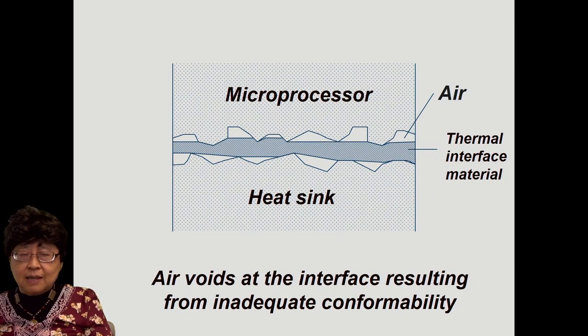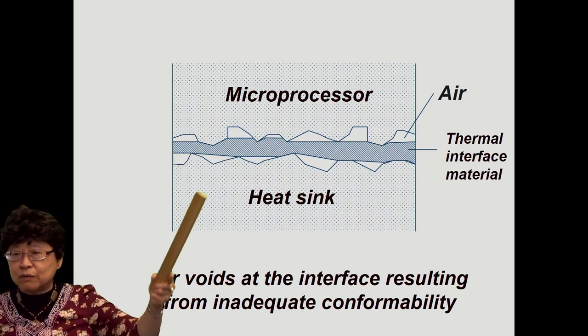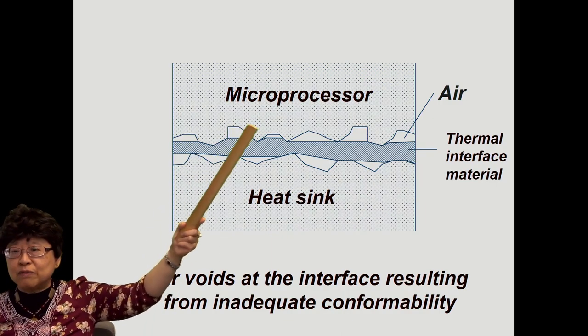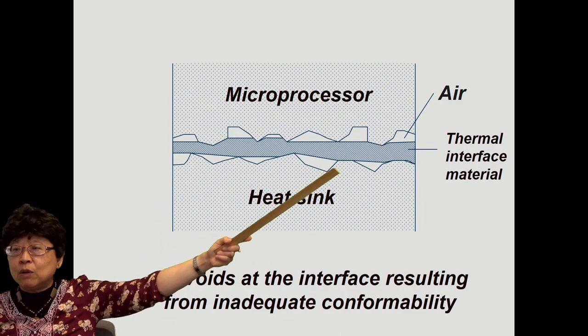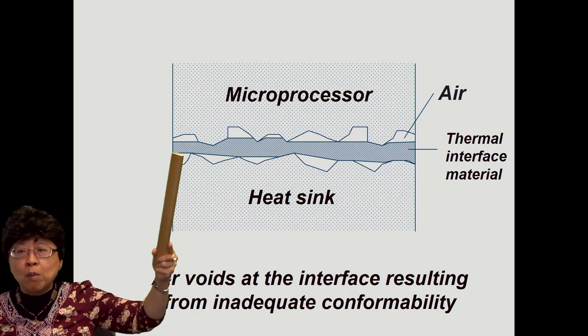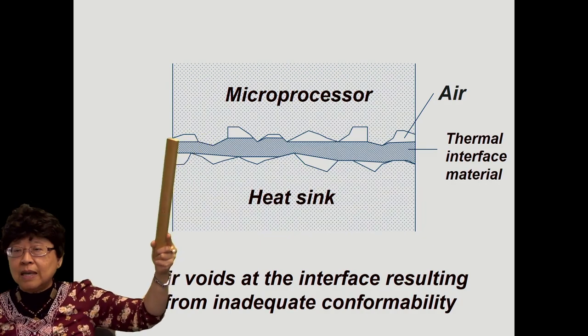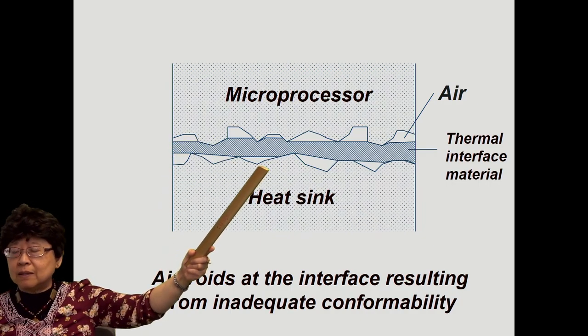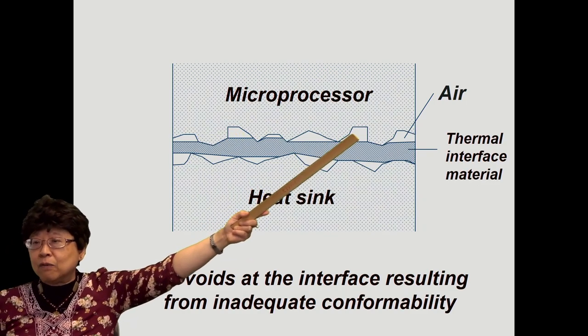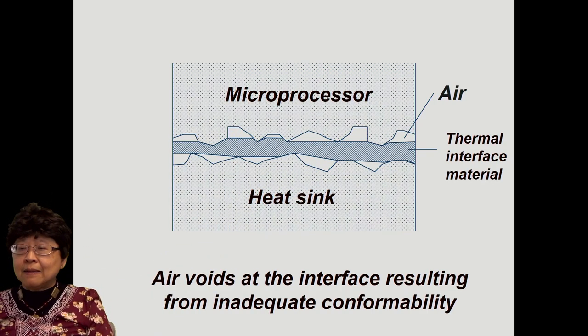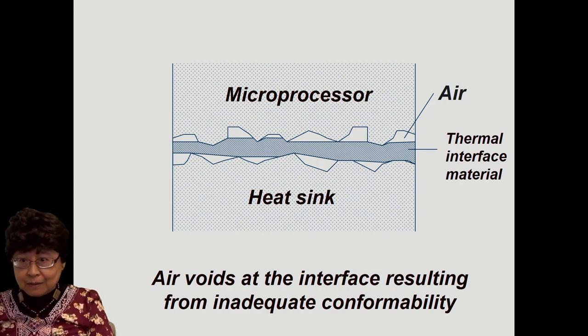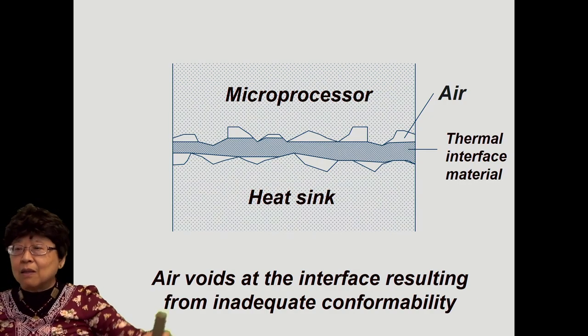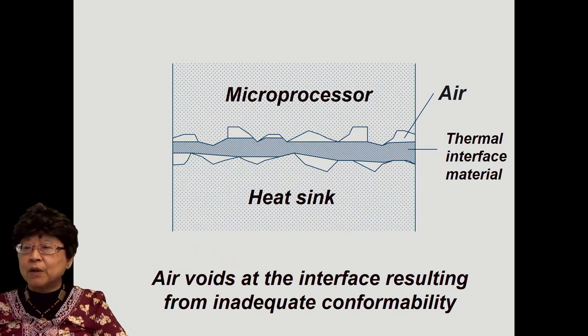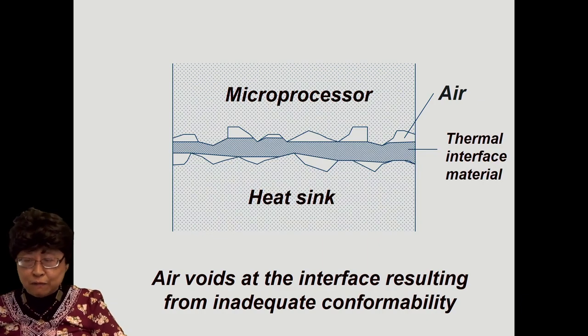Now, no surface is ever perfectly smooth, even if you mechanically polish it. And so you have two mating surfaces. This is a blown up view. Each surface is not perfectly smooth. And if your thermal interface material is not conformable enough, it would not go into each of those air voids enough. So you have air pockets left at the interface, and the air is a thermal insulator. And so this is lousy thermal interface material. So the thermal interface material has to be very conformable, not just thermally conductive.